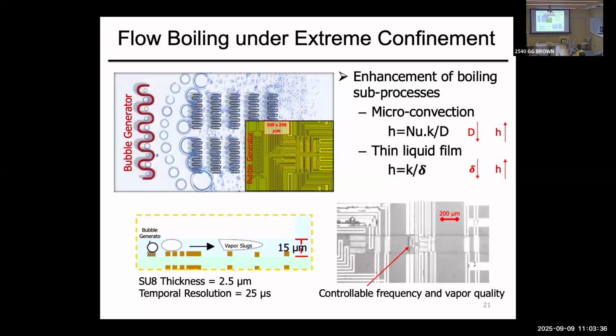So we decided to actually do an experiment, and we did it with channels of different heights. These are not structures, these are just sensors, and the schematic is not representative. Some folks from Purdue and Georgia Tech sent a fluid. We wanted to see why they are not getting the heat transfer coefficient that theory suggests. I said, if there is a 1 micron, 2 micron layer of fluid, the heat transfer coefficient should be an order of magnitude higher than they have observed. Why is that the case? So we have these bubble arrays that we can now produce. This whole test setup is 200 micron by 200 micron. We can provide bubbles at different frequencies, and we can always get a film, with more frequent film formation.